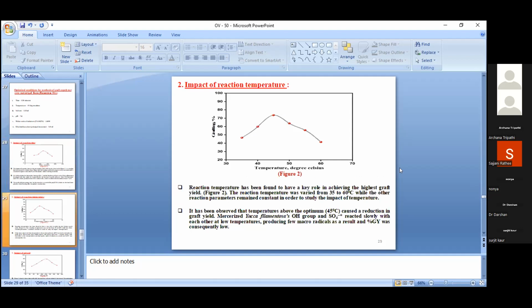The reaction temperature was found to have a key role in achieving the highest graft yield. The reaction temperature was varied from 35 to 60 degrees Celsius, while other reaction parameters remained constant, in order to study the impact of temperature. It has been observed that a temperature above the optimum caused a reduction in graft yield.